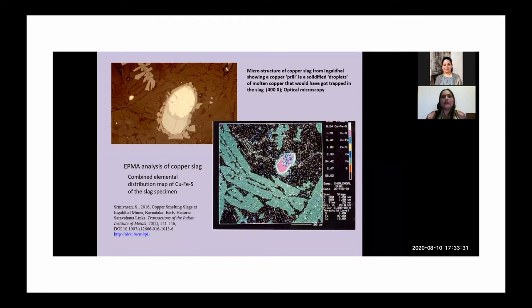And in this case, apart from microscopy, of course, I think by now you would all be familiar with techniques of analyzing materials such as scanning electron microscopy and electron probe microanalysis and such like. And so here what you're looking at is some further analysis done using electron probe microanalysis, wavelength dispersive spectroscopy. And here you see that there are other interesting things that you can do with the use of EPMA analysis, which is described as the elemental distribution map. You can do a combined elemental distribution map for different sets of elements. So that gives you an idea of the ways in which the elements segregate through the slag and so on.